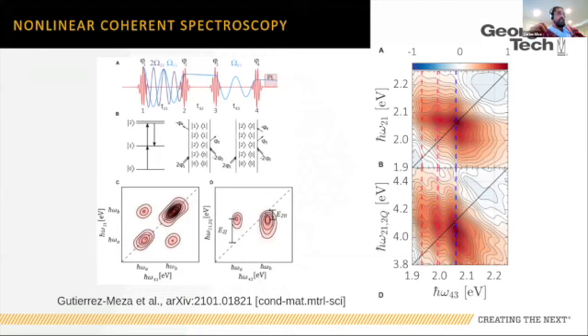It turns out that when we do this trick with Natalie Stingelin of turning the H aggregate into a J aggregate by essentially blending it with a very polar polymer, we can have the predominantly H aggregate in PBTTT or P3HT become a predominantly J-like aggregate. We see that the 0, 0 in those systems shifts from here to here with some structure. So we're going to assign these things as a weak signature of the J aggregate in this hybrid H system that we always expect.